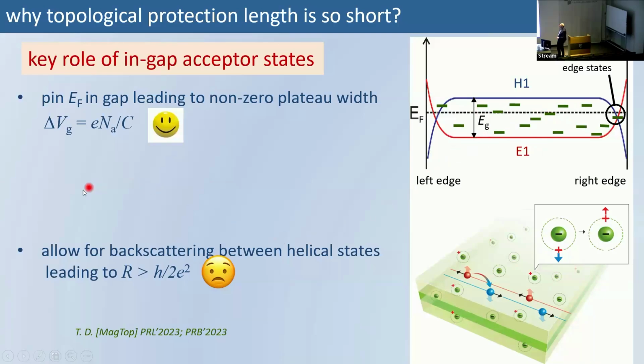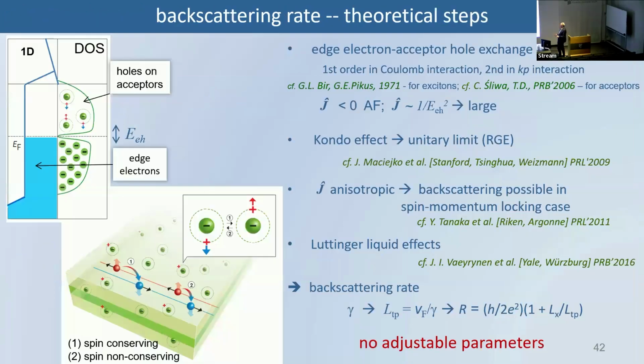But now what also this impurity gives, this impurity has a non-zero spin, and therefore there is possible scattering between these two spin states. This impurity carries a spin, and there could be spin exchange between this electron and this helical state here, impurity reverses spin, and spin is kind of conserved. So this is the kind of model which we propose to understand this weak degree of quantization in this case.